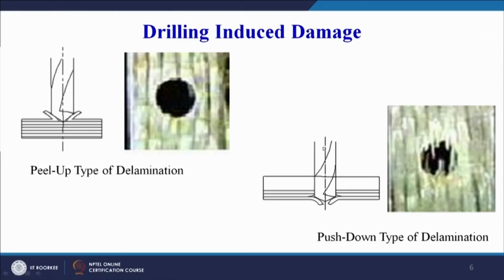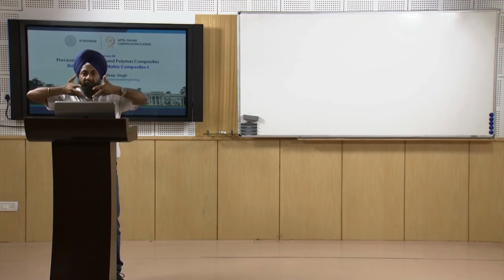Similarly, when the drill tends to exit the laminate, the bottom layer tends to open up, and they debond from their sister layers or debond from their top layers. So the bottom layers tend to open up because of the higher thrust force being generated because of the drilling action. So that is called the push down type of delamination. The drill tends to go out from the composite laminate and it forms a damage in the form of push down type of delamination. So you can see that there is a peel up type of delamination, there is a push down type of delamination.